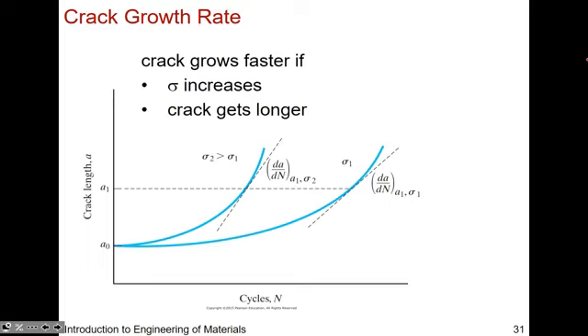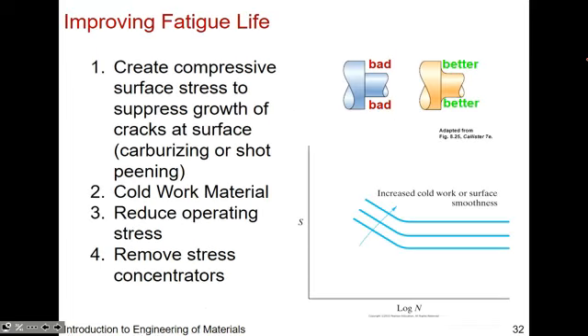As I mentioned, crack growth can accelerate. So if your small crack becomes longer, it's not a linear elongation. It's not 2x and 3x. It could be 1x, 2x, and then grow exponentially, as you can see here, okay? So that's something to keep in mind.